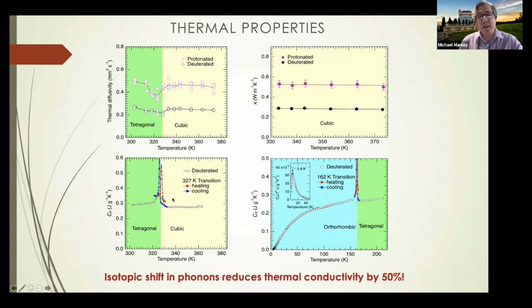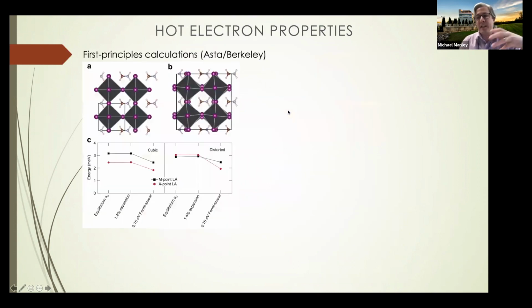Now, to convert this into thermal conductivity, what you need to know is how much heat capacity is being carried. So we measured this, but it doesn't change too much because that's basically just determined by the population of all the modes, and the modes are going to be all populated at these low energies anyways. So it doesn't really change the outcome, but the bottom line is that the thermal conductivity was decreased by about 50%. So this is exciting because this is what we want to see, because remember, we want to basically insulate the electrons and hole charge carriers from losing heat. And when you reduce the thermal conductivity, that helps. And I also want to point out this thermal conductivity is really low. So 0.5 watts per meter Kelvin is already really low. We're down at 0.29. That's basically like a plastic or something.